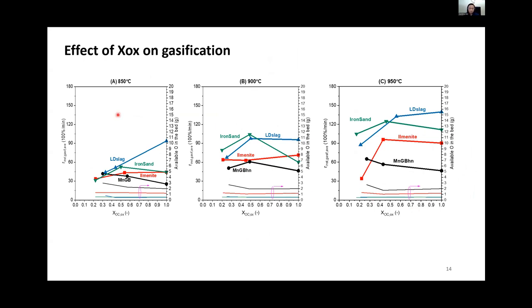Average gasification rates are plotted as a function of XOX, and the thinner lines are the available oxygen in the bed. In the case of LD slag, iron sand, and ilmenite, the higher XOX value means the oxygen carrier is more oxidized, and when it is more oxidized, the gasification rate is higher, whereas the manganese ore has an opposite trend. LD slag and iron sand have the highest gasification rates in all the cases, although there is less bed oxygen available. Temperature increase leads to faster gasification, and at higher temperature, the gasification rates with iron sand and LD slag are much higher than the other oxygen carriers.